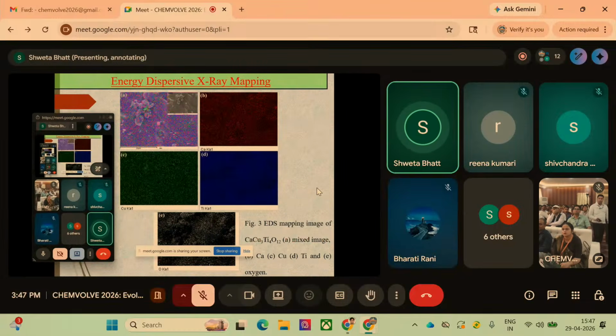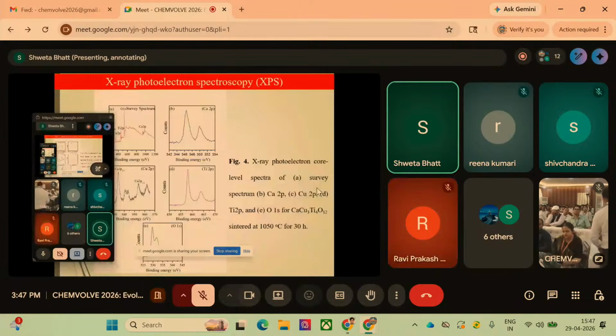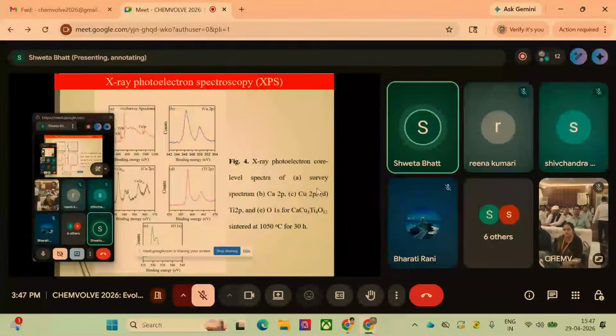We have also used the energy dispersive X-ray mapping and seen that all the atomic elements like calcium, copper, titanium, and oxygen are present uniformly. So this method provides the formation of a uniform composition of the material, clearly shown by the EDS mapping. Here we have also shown the X-ray photoelectron spectroscopy, XPS. In the case of XPS, we have seen that calcium, copper, titanium, and oxygen are present.